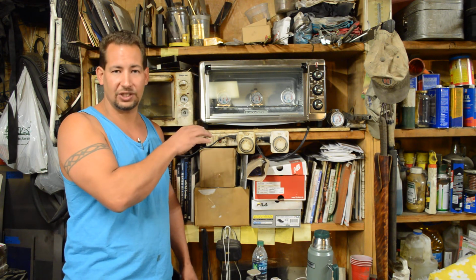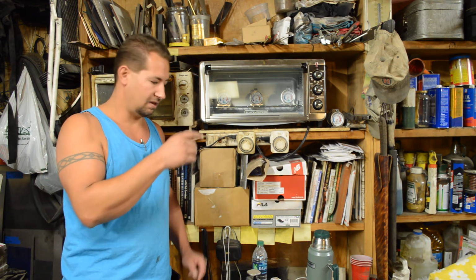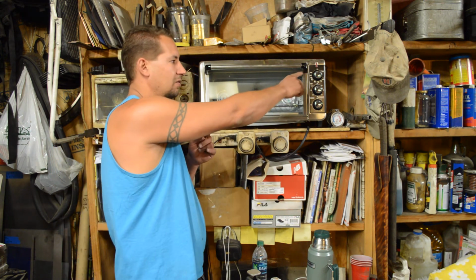So the other day I made a new steel order for 440C and 1095, and I bought a full sheet of 440C. 1/16 inch thick, 2 foot wide, 6 foot tall. It was cut into two pieces just to make it easier on the UPS guy, but that's about the smallest I'd really like to order steel, and even that was, I think it was probably $700 by the time shipping was all said and done. And that is an awful lot of steel, but I can go ahead and set my toaster, double check the heat treat with a new piece of steel, and then I know that this corner of that piece of steel and this corner of that piece of steel are probably fairly close to being the same.